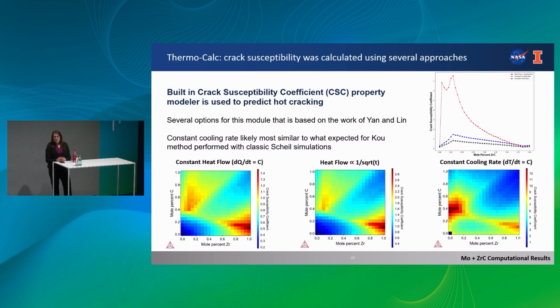So if you try to put that into a graph that makes a little bit more sense, as you can see here, there's actually 3 different approaches to use for this crack susceptibility coefficient modeler, but all of them show that they have a peak all around the same area. So we decided to use the approach that was the most dramatic, but also is likely the most similar to traditional Scheil solidification simulations, which is the constant cooling rate approach.